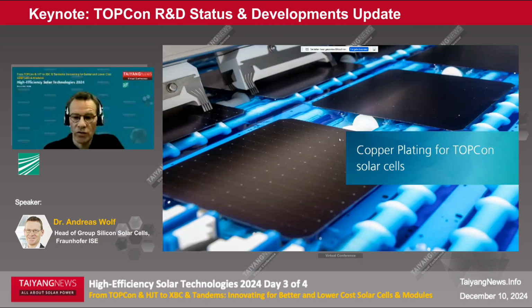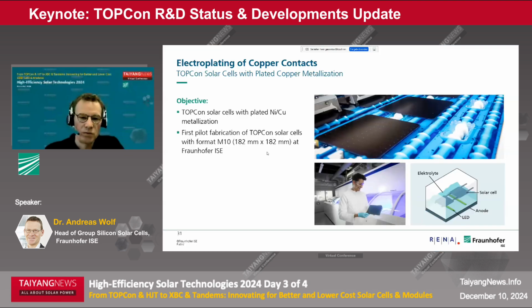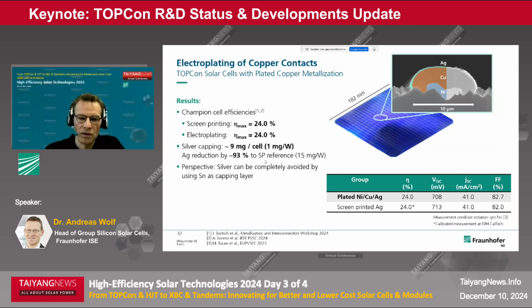One challenge that we all face is silver consumption. And here one alternative that we promote is plating of copper contacts instead of silver, printing silver pastes. And we have a pilot fabrication at ISE together with our industry partner RENA, where we fabricate large area TOPCon cells with plated contacts. And we were able in the first batch to already achieve efficiencies that are similar to the screen printer reference. This is the cell that you saw on the slides before.